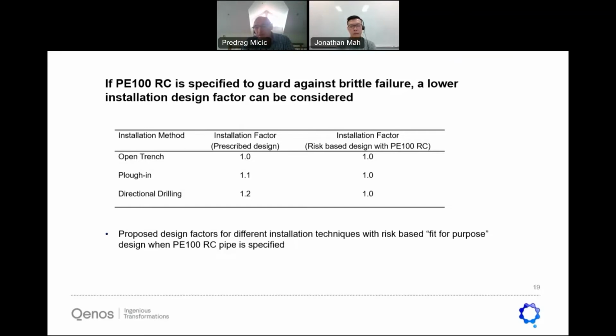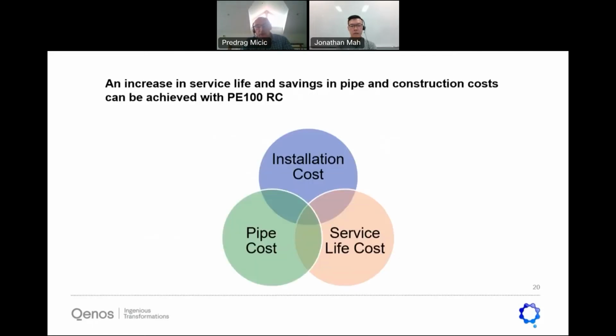If we use the right integrity measure, which is the material with higher resistance to that notch, we may be able to drop the design factor to 1, for example, and base our design on a fitness for purpose design where PE100 RC pipe is specified. So that testing program certainly supports that, and this means that if you use PE100 RC, the risk associated with slow crack growth can be dealt with in this way. So it's just one of the examples.